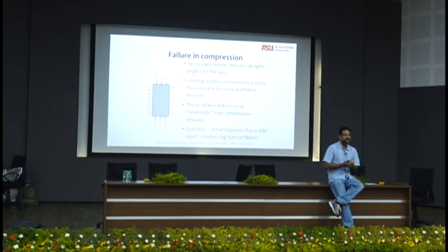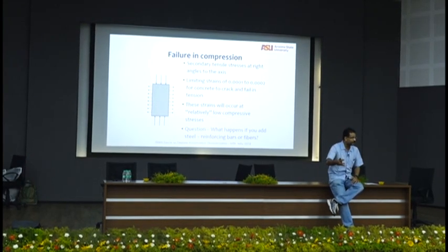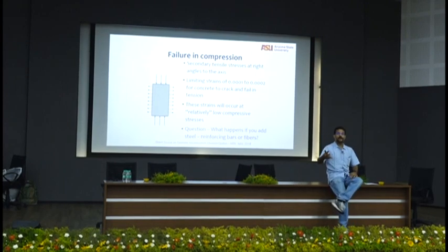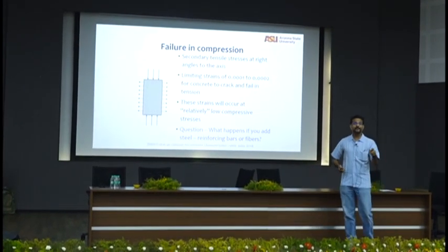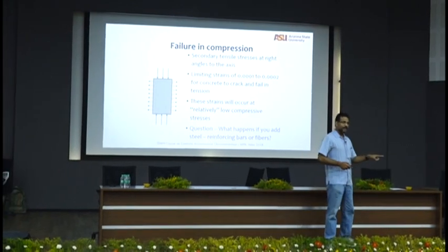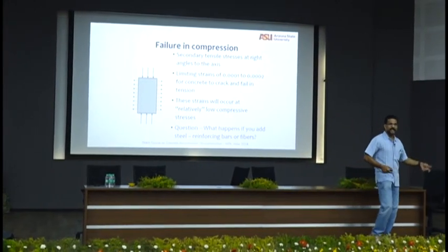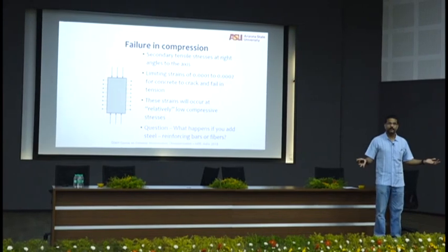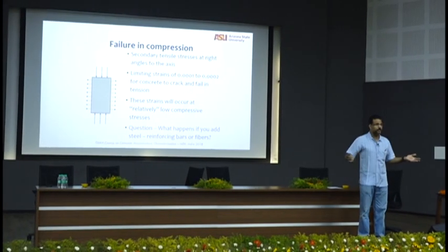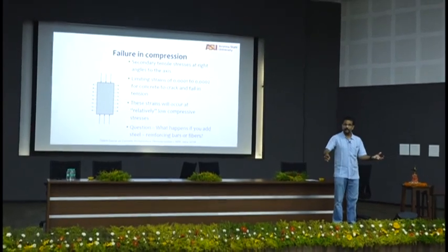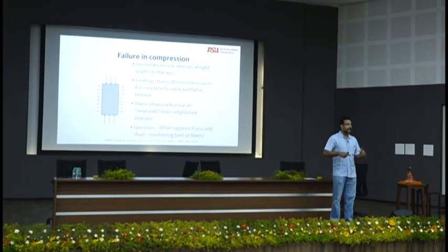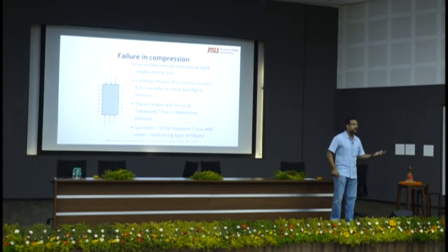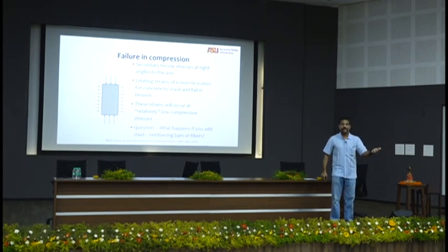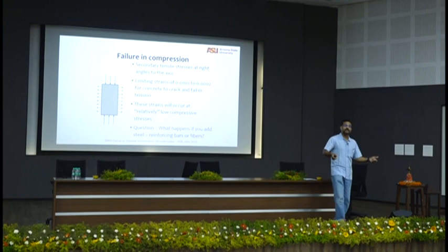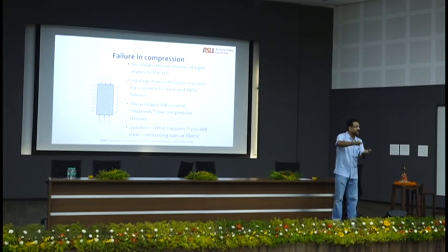And several localized failures coalesce to give what we perceive to be a global failure. And you cannot design for a global failure, therefore you have to design for a local failure. Local failure meaning controlling things at the local scale. What is local as far as concrete is concerned? If I am looking at concrete with my naked eye, what is local? Aggregates and cement paste. If I am looking at cement paste under a microscope, what is local? CSH and calcium hydroxide. If I am looking at CSH further under transmission electron microscope, what is local? The layers of CSH, right?